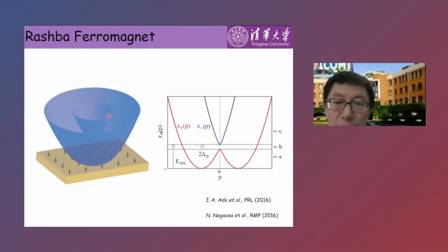The observation of the Rashba split band and its interaction with the topological surface state is not trivial. First, it will contribute significant carriers to the system, which will play a role in the transport of the material. Secondly, it provides a platform to realize the Rashba ferromagnet, considering the surface ferromagnetism of the sample. As proposed by theory, the spin-orbit coupling and ferromagnetism may open a gap at the band crossing point. Such a system is attractive for the anomalous Hall effect and possibly also for the quantum anomalous Hall effect.